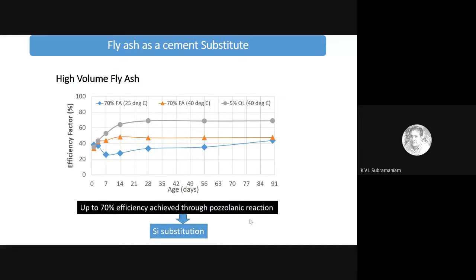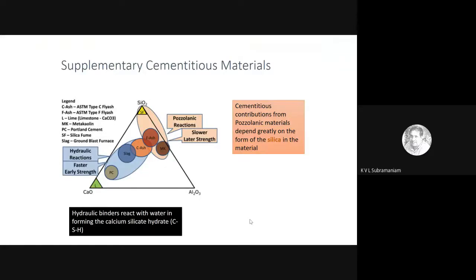So that means that you can only maximum achieve 70% of the strength using a pure cement system. So just to show you that other supplementary cementitious material, typically we have this representation in what is known as a ternary diagram. In a ternary diagram, you basically have calcium oxide, alumina, and silica. And basically based on the composition of these materials, they will basically come as a point on this ternary diagram.